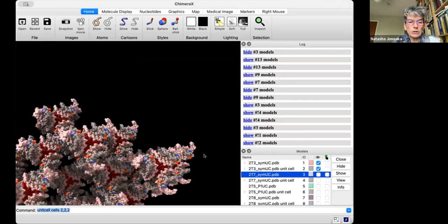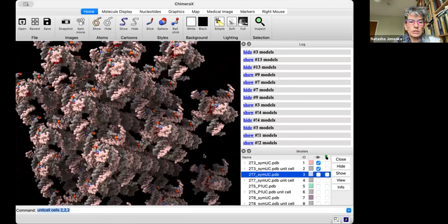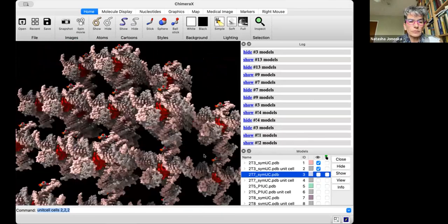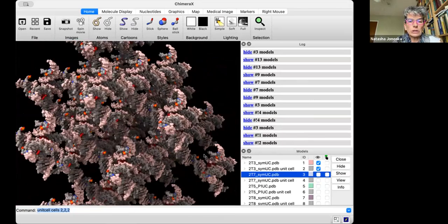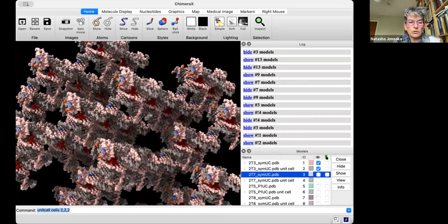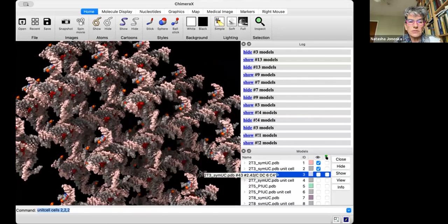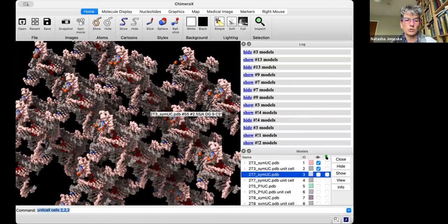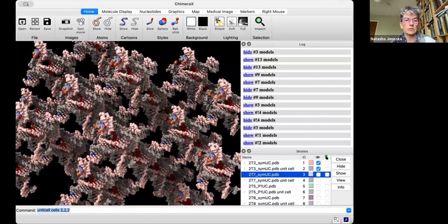And if I look at the crystallographic structure, this is the crystal that is formed from that. The crossings of the sides of the triangle are opposite to the crossings of the sides of the triangle in the 7 nucleotides. The original was 7 nucleotides from junction to junction. This is 3 nucleotides from junction to junction. The central strand is very difficult to see.